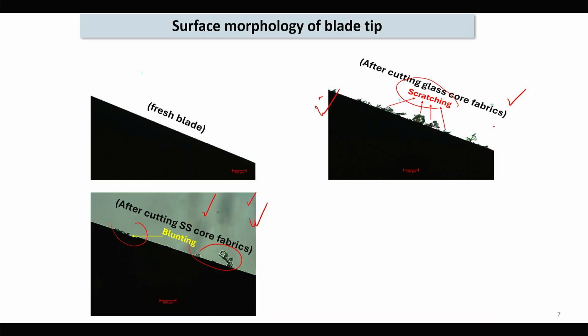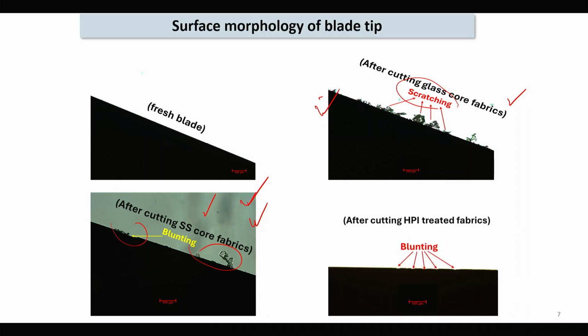With normal polymers, blunting takes time, but when we introduce hard particles along with the glass core and the stainless steel core yarn, we can see proper blunting at the tip. Depending on the type of obstruction provided by the glass core or stainless steel core, along with the hard particle impregnation, the blunting pattern changes, and here you can see throughout the surface the blunting takes place, and the surface becomes totally uneven, and that is the reason for the increased cut protective performance.